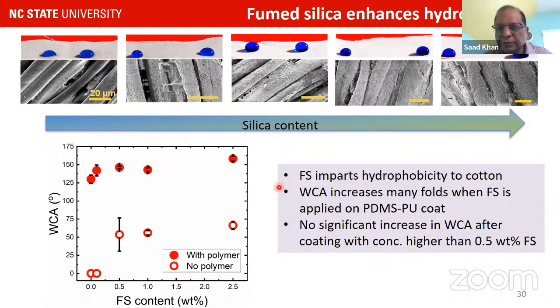If you do just pure fumed silica, we do get a substantial jump. If you do it with PDMS, PU, we see some increases. And then after a while, if you add a little bit of fumed silica, it seems to have saturated. We don't see any increase.